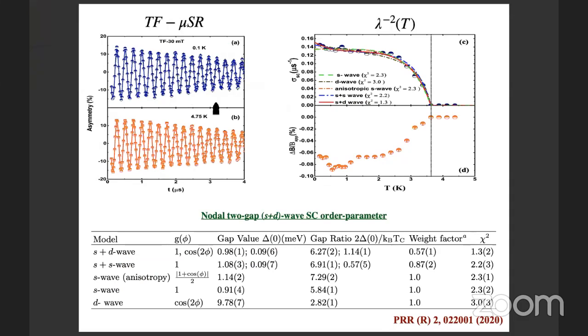Okay, so these are the transverse field MuSR time-dependent asymmetry spectra, and we have fitted these spectra and calculated the superconducting order parameter as a function of temperature. The circles represent experimental data, and these are fits using different models. Here also it is very interesting to note that we have multi-gap superconductivity, and the best fit is obtained using the S+D model.